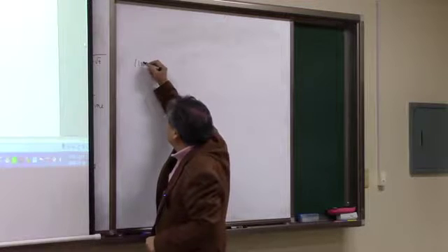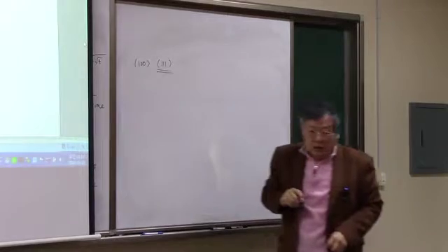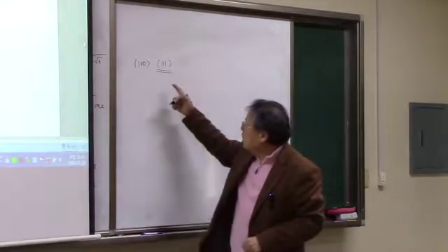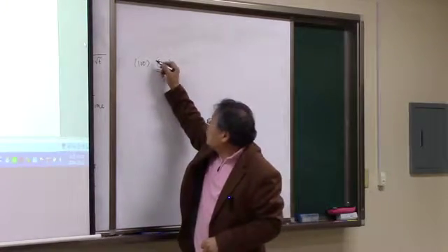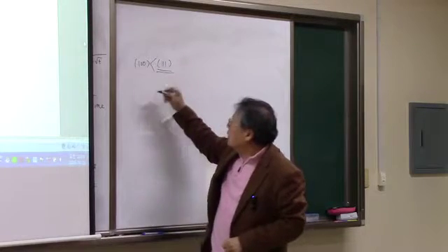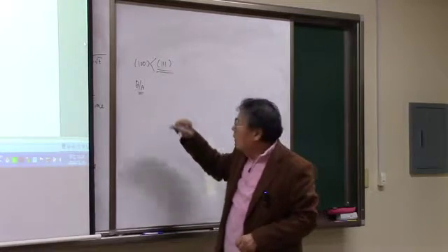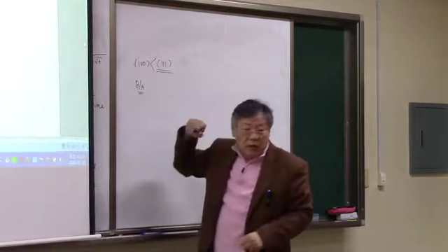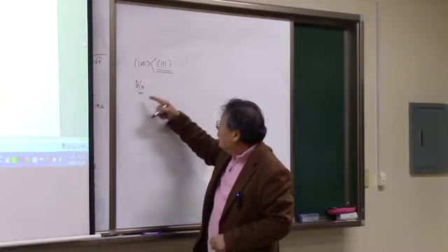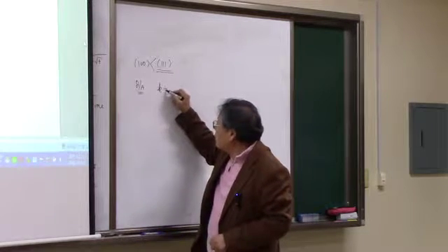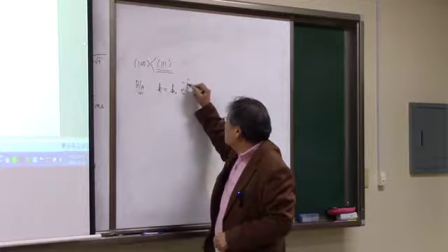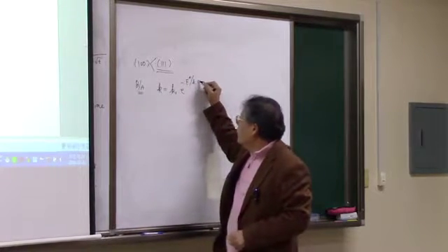We have seen that 110 and 111, this is a close packed density we have in the silicon, and the atomic density is much greater here, and the B over A constant is somehow an Arrhenius type thing. Now, for the surface reaction constant, for example, K is e to the minus E star over kT, okay?